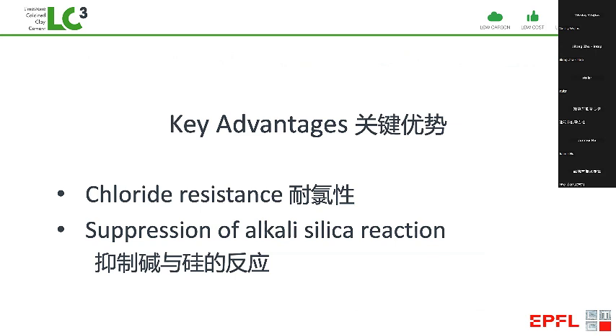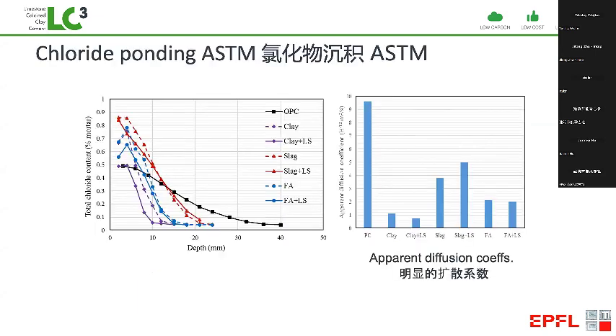So just to talk briefly about some of the key advantages, we have much improvement of chloride resistance and total suppression of alkali silica reaction. So looking at the chloride resistance, this shows a comparison of different materials. The black line is the reference pure Portland cement. And you see after only 6 months, the chloride penetration is about 40 millimeters. When we have different blends with slag, this is improved, and blends with fly ash, this is improved still more.